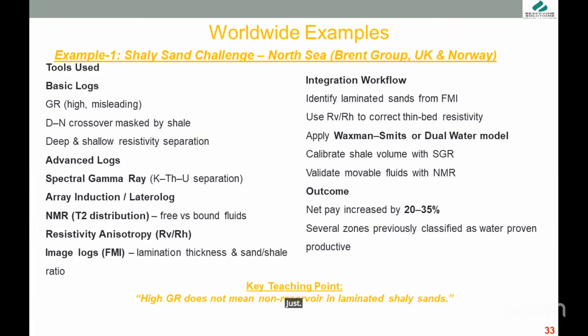Image log is just to see the thin beds, because the image has a high vertical resolution, 0.2 inch, to detect the limitation of the thickness and the sand shale ratio, from conductive, resistive, conductive, resistive. The workflow identifies the thin sand from FMI, uses RVRH to correct thin bed resistivity, just to get the correct resistivity to correctly estimate the water saturation. Apply Waxman-Smits or dual water model, calibrate shale volume with spectral gamma ray, validate movable fluid with the NMR, just to see after I have done all my workflow, finally, whether this reservoir can produce a good amount of hydrocarbon or not.